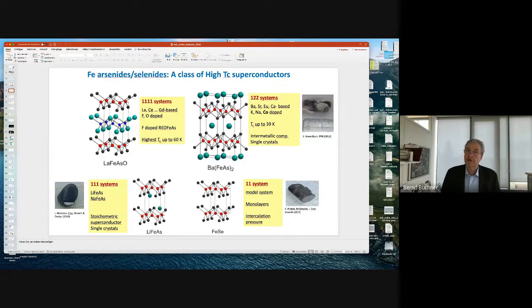And this is a very special situation. In some sense, we combine an oxide with a more metallic layer. The other, more famous compounds of these iron-based superconductors are more intermetallic compounds. So this complicated lanthanum oxygen layer is here replaced simply by a barium atom. So in these 1-2-2 systems, and these are by far the most studied systems, we have a simple intermetallic compound in some sense. And for such intermetallic compounds, you can then grow large-scale single crystals. That's from our own work. And that's also the case for other systems like lithium iron arsenide or sodium iron arsenide, the so-called 1-1-1 systems.